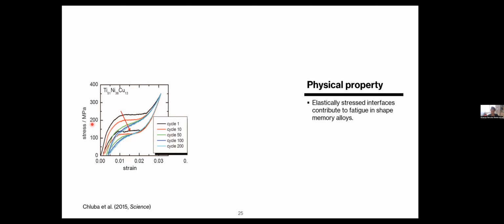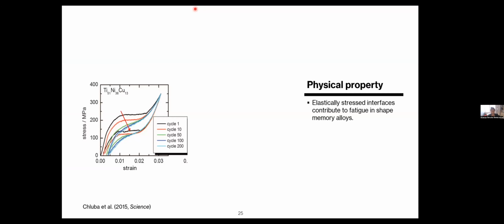Now, if you go back to this microstructure and ask how I can change the lattice geometries of the material so I can form an exactly compatible interface, or eliminate the stresses at this interface, I can expect this material to cycle longer without developing fatigue. And that was a geometric constraint that was proposed in a recent work, which identifies a specific combination of lattice parameters. So they use that as a guide to change the composition of this alloy.